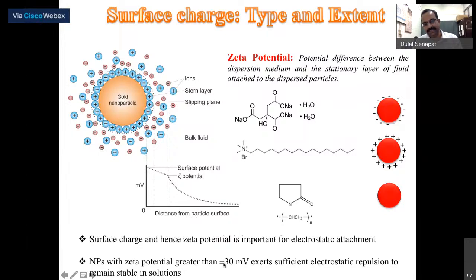If the zeta potential of the particle is higher, that means the charges are concentrated more onto the surface, and as a result one nanoparticle will repel the other nanoparticle, so they cannot come close to each other. So they will not agglomerate, and as a result these particles will remain stable. That's why any nanoparticle with a zeta potential greater than 30 millivolt is pretty stable in solution. So when we synthesize nanoparticles, we try to make nanoparticles with a much higher zeta potential so that they remain stable for a long time.